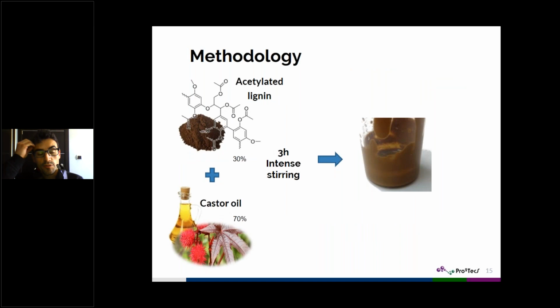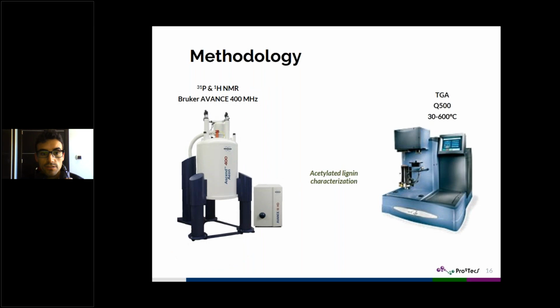Well, just for the preparation of the oleogels with lubricating properties, we just mix the acetylated lignin and the castor oil. Below 30% acetylated lignin content, we obtain some separation. So we selected 30% acetylated lignin content for the preparation of the gels. And the preparation was just done by intense stirring for 3 hours. And you can see this is the product that we obtained after that oleogel formation.